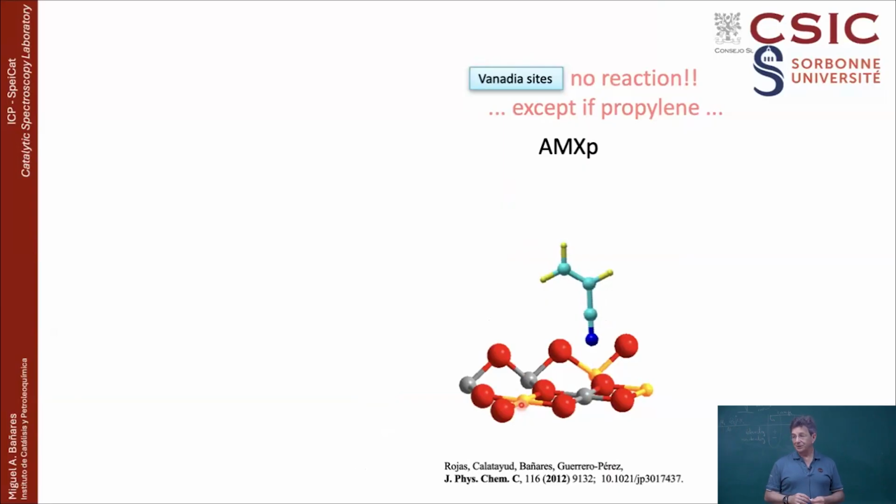Well, we were using density functional theory. Basically, to do that, you have to describe the lattice of the vanadium antimonate, which is a rutile structure, like the one I'm drawing. This is just the surface of the rutile lattice structure. It's a periodic model, so you make a unit cell and you repeat ad infinitum. So you can calculate what happens at the surface of this material when you're adsorbing molecules, like propane, propylene, oxygen, ammonia, and that's made by computational chemistry, density functional theory calculations. And then you can observe how strong different molecules are adsorbing on different sites.